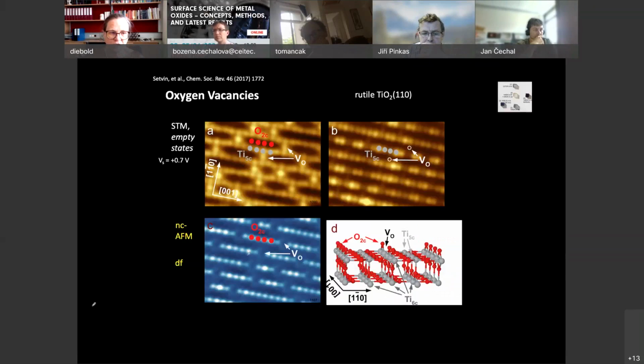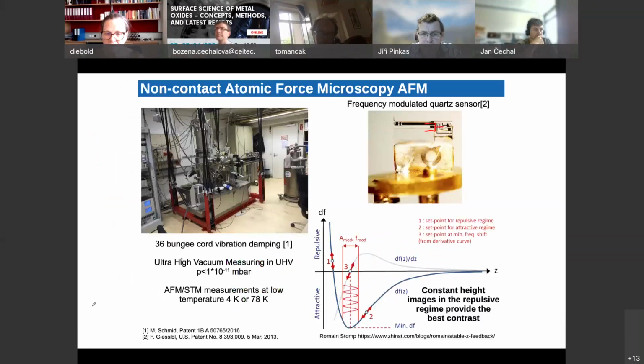So what I've shown you here is the change in the resonance frequency at a certain position in front of the surface. And depending if you're in this position or in this position, actually if you're very close to the surface, already in repulsive interaction, then you get a very high contrast. So the contrast that I showed you before is really very close to the surface. In the repulsive regime, we get a high contrast.